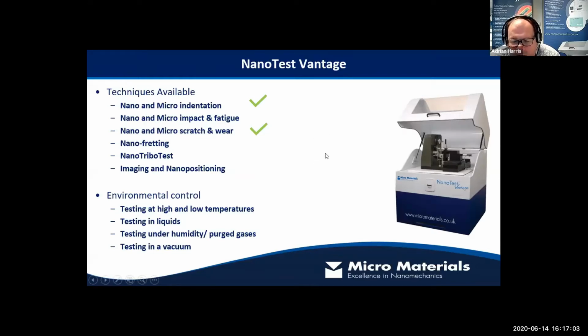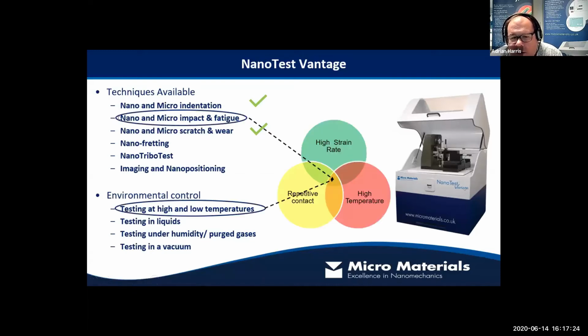We don't want to do very heavy, large-scale scratches where the stress maximum is in the wrong position. Nano scratch is too small a technique for these. Really, nano scratches are for things like coatings up to around half a micron thick. So what about this high temperature, high strain rate combination? Well, here we can combine our nano and micro impact and fatigue testing with the high temperature capability that we have under our environmental control options. Put these two things together and it puts us right in the middle of this Venn diagram.